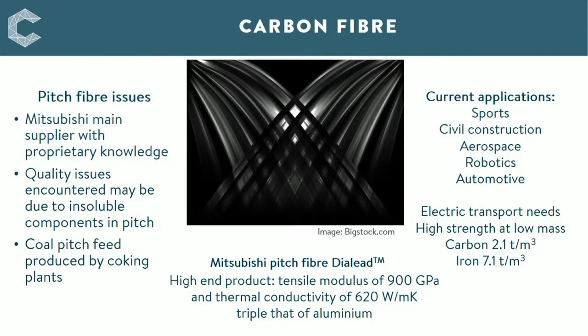There are fewer stages for pitch fibre processing, but there is more risk of off-spec material as pitch contains such a wide range of components, and so the carbonization process has to be more tightly controlled. The leading manufacturer of pitch fibre, Mitsubishi, may be selecting part of the pitch very carefully, as well as using very tight processing conditions. Certainly, recent independent research has shown that removing quinoline soluble matter improves the quality of the fibres. Although PAN fibre has superior properties, the market-leading Dialead pitch product is now used in space applications.